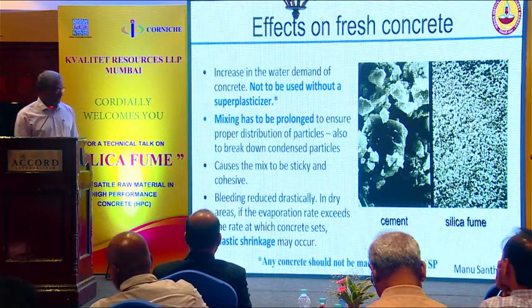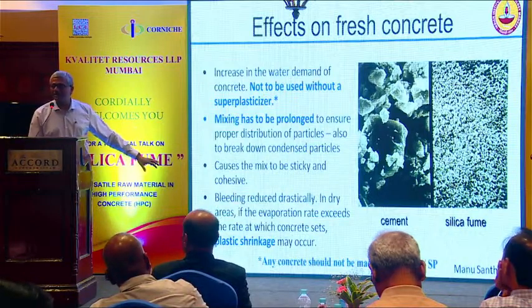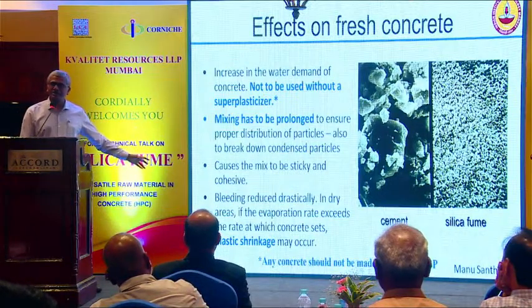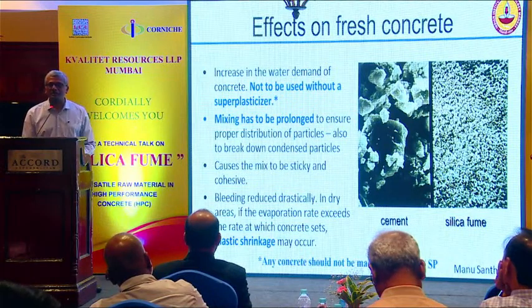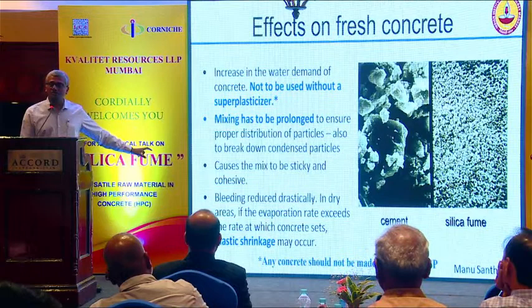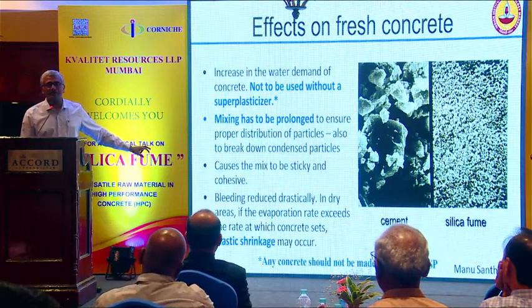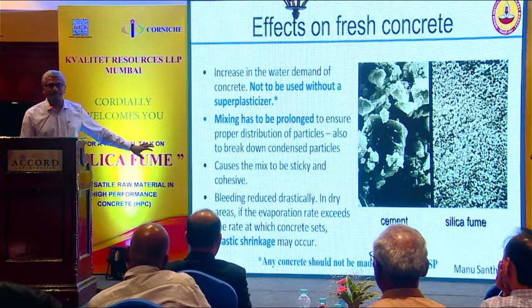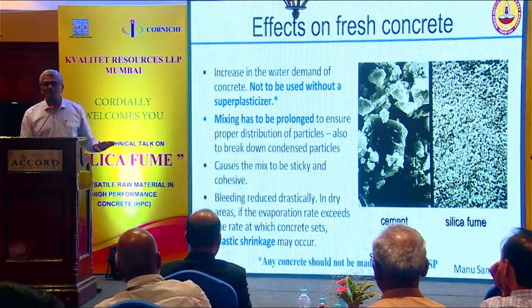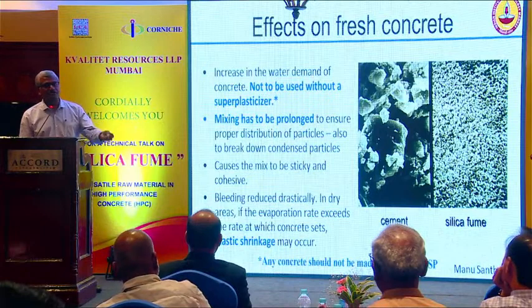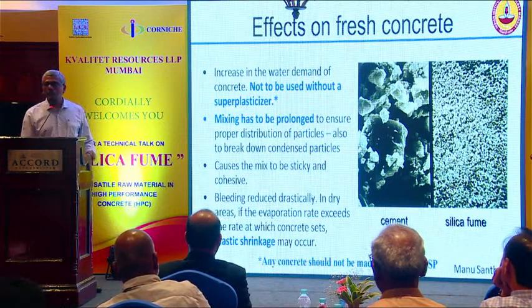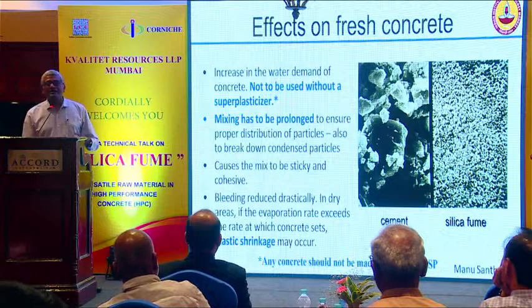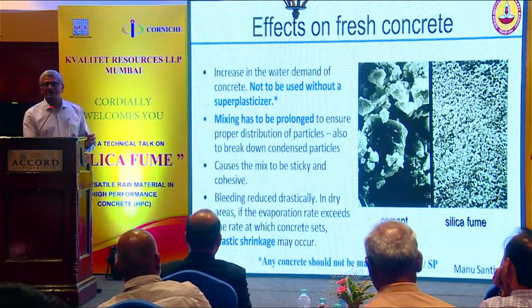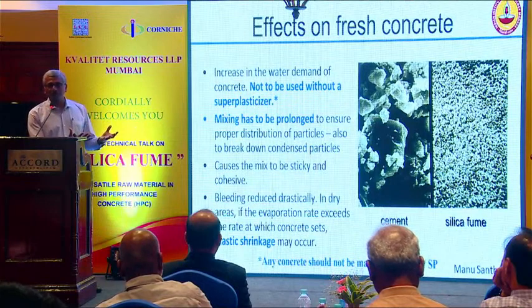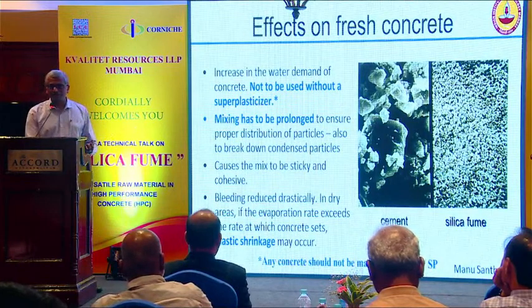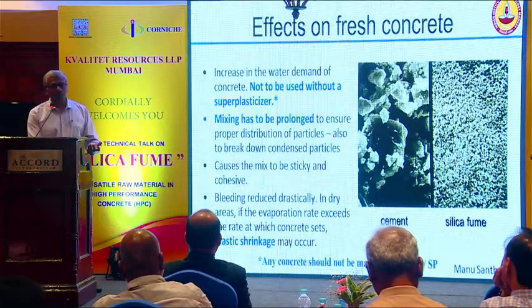because again, any fine material will do that, right? Stickiness will increase. But more important, you need to understand, whenever you're using not just silica fume, any mineral admixture as a replacement of cement, you can expect that if you don't pay attention to the concrete in the early stages, plastic shrinkage problem will definitely happen. Okay? Any concrete with mineral admixture, not just with silica fume. You take fly ash, slag, anything. Because most of these materials are finer than cement. Secondly, as I said earlier, because you're replacing a denser material with lighter, the paste volume is going up. You have more paste in your system, right? So when you have more paste, more shrinkage.